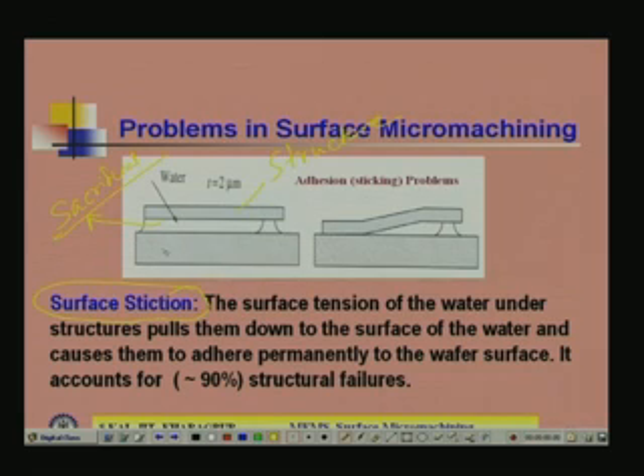Okay. Now, if you go on etching, with a long beam here, there is a possibility, because of the surface tension of the liquid etchant. If it is a small area, this region will stick. You can see this particular portion sticking; in surface micromachining, long beams will stick here, and as a result it may break here. That problem is known as surface stiction.